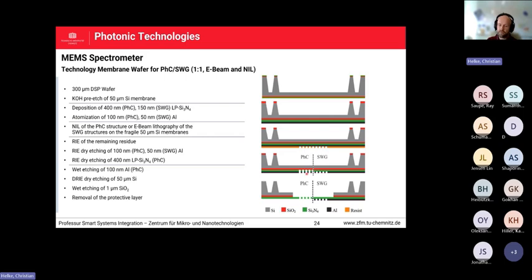We do the etching of the hard mask aluminum, we do the etching of the silicon nitride layer of the left side here, for example, and at the final end here, we release the membrane, meaning we etch the silicon via a Bosch process from the back side. We remove the silicon dioxide, which acts here as an etch stop, by the deep reactive ion etching from the back side, and then we remove the photoresist on the front side.